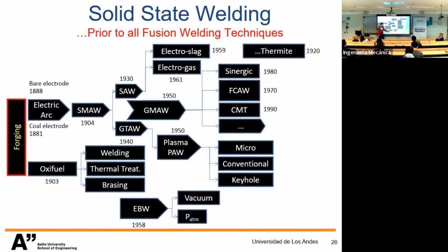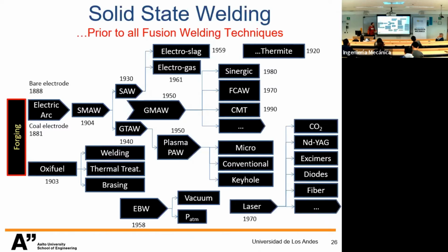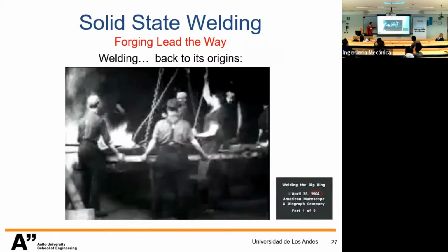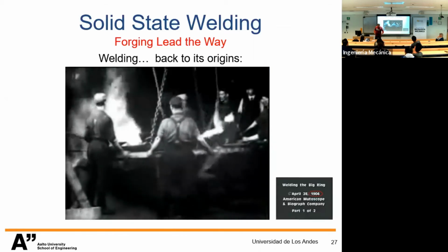A very distinctive, probably quality-wise the best solution, is actually electron beam welding, operating from vacuum to atmospheric levels of pressure, and also laser, with some more limitations of the photonic interaction between the material surface and absorption. We have different active media that adapt also to different domains of application. So these are used in joining, but also in cutting, in coating, and processing of surface. This is the domain, also in thermal treatment, where this field of technology is applied. And so forging is at the origin of joining of materials.